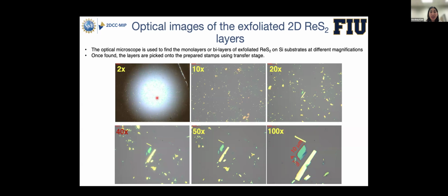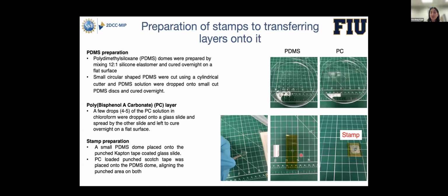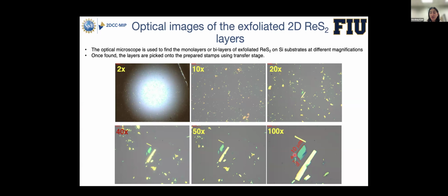So here are the different magnification images, or optical images, of the material. We could find a 10x4 micron layer, which we were not expecting to be a monolayer, but it could be multi-layers. So we wanted to transfer this 10x4 micron multi-layer onto different substrates.